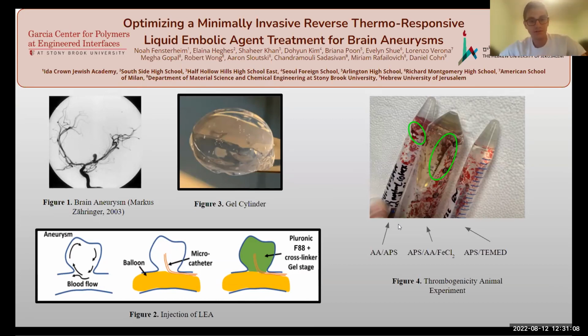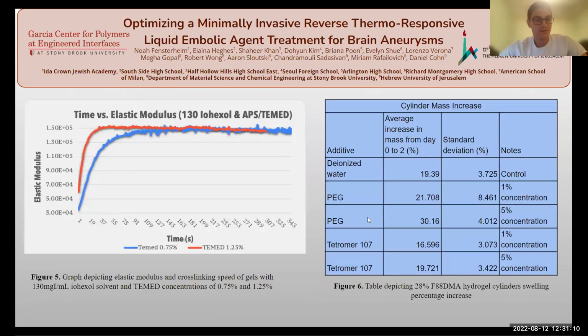Could you move to slide 2, please? Through rheometry, we found that gels with higher TEMED concentration of 1.25% and lower contrast agent concentrations of 99 milligrams per milliliter took less time to cross-link and reach their maximum stability than their 0.75% TEMED, 130 milligram per milliliter counterparts. This is important because we want the gel to cross-link as fast as possible after injection and remain stiff so that it doesn't get washed away by the bloodstream.